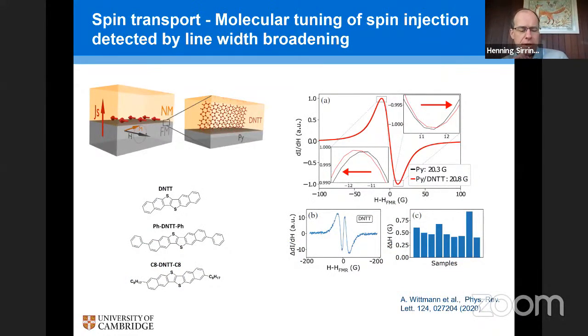And then the third area that my group is investigating is spin transport in these molecules. I show you here an example of a very simple but elegant measurement to investigate spin injection into organic semiconductors. We have an interface between a ferromagnetic system, permalloy, and we deposit this organic semiconductor, again the same molecule, DNTT, on top of the ferromagnetic surface. This is an experiment that was done by my PhD student, Angela Wittmann, at the time. She studied the ferromagnetic resonance properties of this ferromagnet with and without the organic semiconductor present.